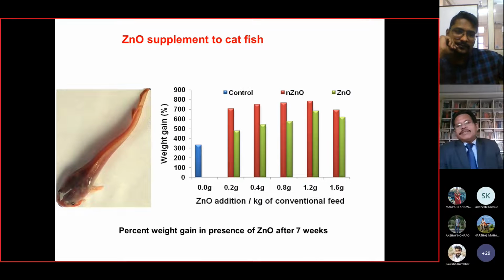One experiment has also been observed that zinc oxide can be used as a supplement for catfish. So this is a fish, and it is observed that this food is given. This is the control, this is the nano zinc oxide, and this is simple zinc oxide. After addition of nano size zinc oxide, the weight of this fish increases, as shown here. See, in this way, 0, then 0.2 gram, 0.4 gram, day by day we have given, and we observed this for 7 weeks and saw that there is a gain in weight of the fish because of this nano size zinc oxide.